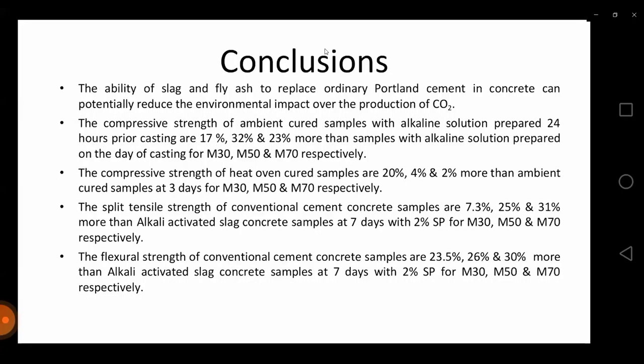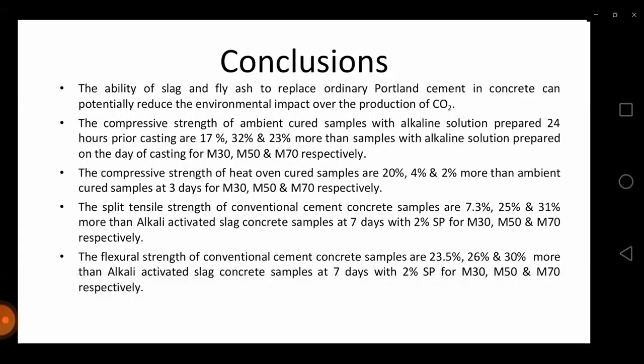So by observing all these graphs and tables, we can conclude the following. First of all, the general conclusion is that slag and fly ash can replace the OPC, that is ordinary Portland cement, in concrete, which can reduce the CO2 released from the cement factories. The second one, the compressive strength of the ambient cured samples with alkaline solution prepared 24 hours prior to casting is 17%, 32% and 23% more than the samples with alkaline solution prepared on the day of casting for M30, M50 and M70 respectively. Again, the compressive strength of the heat cured samples is 20%, 4% and 2% more than ambient cured samples at 3 days for M30, M50 and M70.